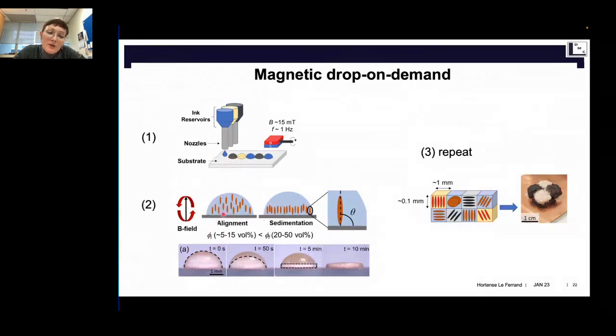This is fairly low concentration, between 5 and 15 volume percent. But when we do this, the particles actually sediment nicely to reach a higher concentration, up to 20-50 volume percent. So it increases the concentration, it sediments, and then the water of the ink dries out, and you're left with a horizontal surface, and inside you have aligned platelets. So that's one drop, and then you repeat it. So it's voxel by voxel printing.